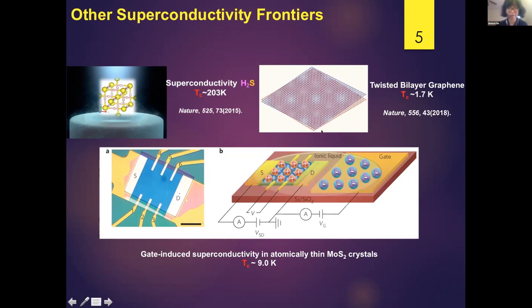So what people did is they made molybdenum sulfide into a transistor, and then they put an ionic liquid on it to make a gate. So this gate-induced superconductivity can be observed in, for example, what I showed here, the molybdenum sulfide crystals. Okay, and I'm sorry, the reference has disappeared. Okay, so the TC can go as high as 9.0 Kelvin.